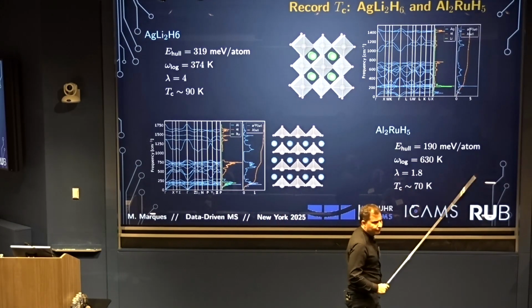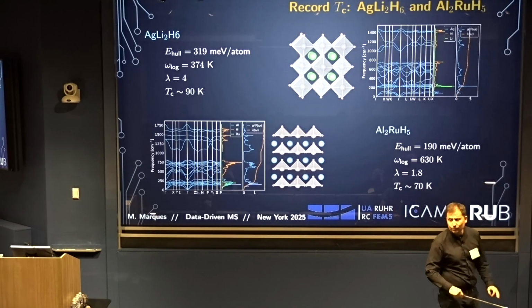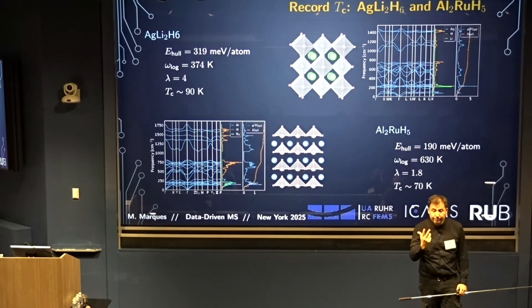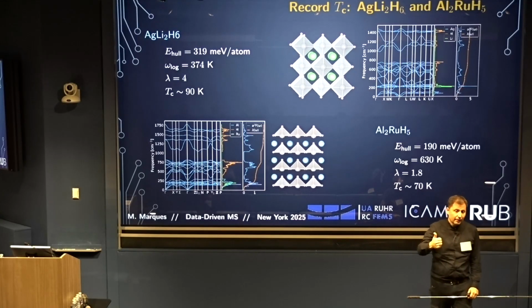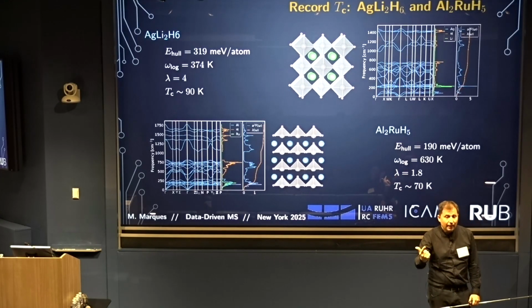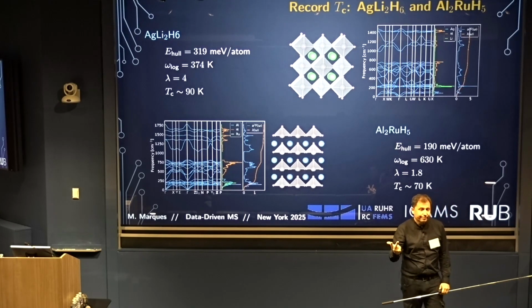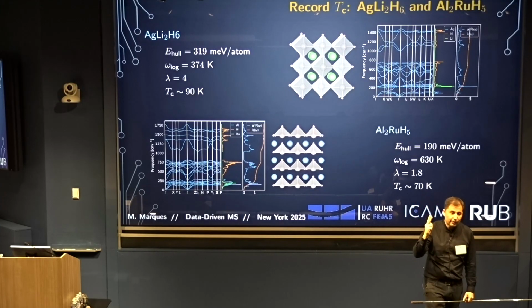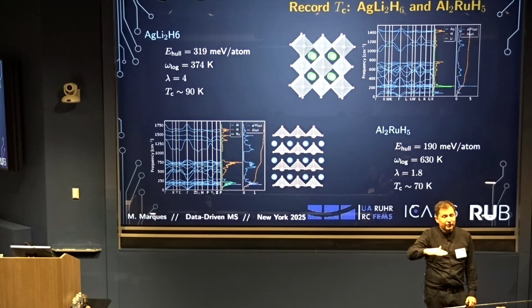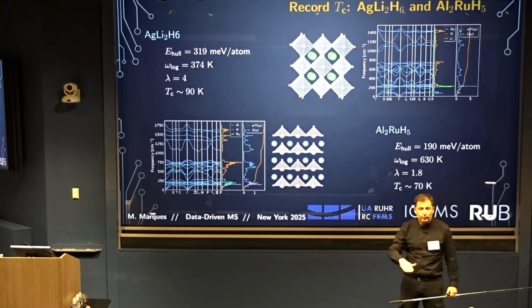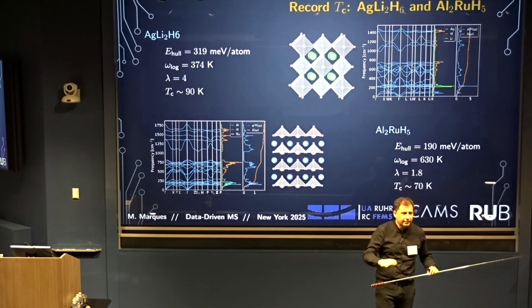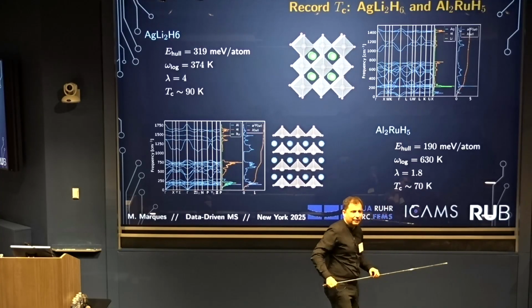There are essentially 3 different paths that you can go to high TC. We only found 3: hydrides, borocarbides, and magnesium diboride and friends. These are the only 3. Immediately after, nitrides. Then come intermetallics. So these are the biggest families that you can have.